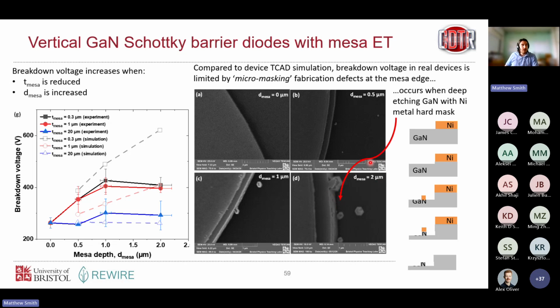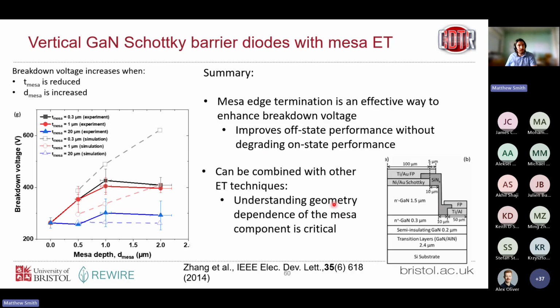And what's actually happening here is when we're making the MESA structure, we use a nickel hard mask. So as we're etching, nickel can redeposit on the surface. So during the plasma etch process, this nickel's not entirely stable, it can redeposit. And then those redeposits act as what we call micro masks. So a bit of nickel's on the surface there, and it's actually masking more of the gallium nitride. So when we strip the nickel mask, we have these additional features which we don't want. And in some cases, they attach themselves to the MESA edge and cause these problems here.